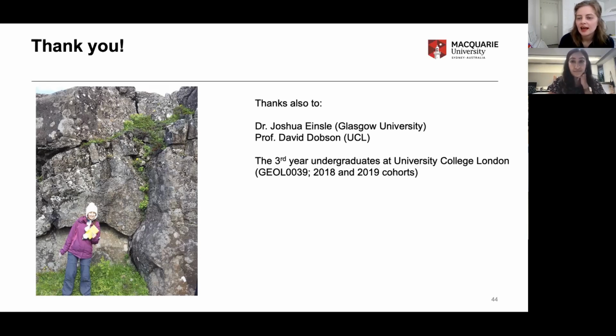Excellent. Cool. Heather said, great talk, Isra. I might have missed it, but what's the minimum grain size and how would it handle skeletal grains? Minimum grain size possible to measure within the automated approach? So I don't think there is a minimum grain size because we're making use of the pixels. So depending on your imaging quality, it will depend on how big your pixel actually is. And that's why, if you've got a very high quality image, the number of pixels per grain will increase. So you'll have better coverage that way.